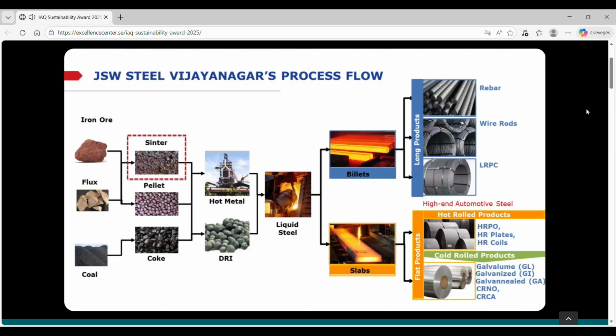This is the process flow of JSW Steel, Vijayanagar Works. The raw materials, that is iron ore, flux, and coal, are processed to produce sinter, pellet, and coke. Sinter, pellets, and coke are charged in blast furnace to produce hot metal, and pellets are charged in DRI shaft to produce DRI. The steel scrap and hot metal are charged in basic oxygen furnace to produce liquid steel.